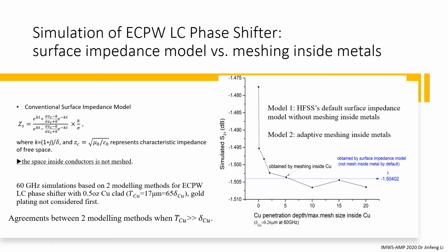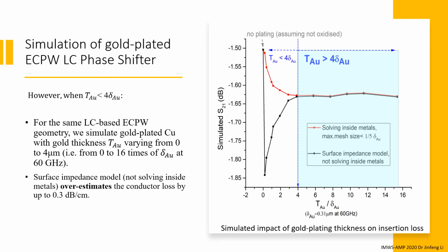The convergence of the adaptive meshing refinement inside the core line metal is shown in this figure. Benchmarking the two different models, we verified that S21 given by the surface impedance model without meshing inside metals agrees with that by meshing inside conductors in this case. However, it is not the case for a thin layer of gold plating on a copper pattern.